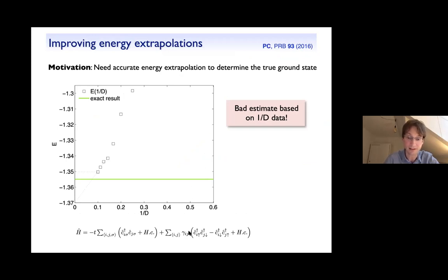That's for an exactly solvable model of non-interacting spinful fermions. The details don't matter, but the exact energy is shown in green here, this green line. And this is the iPEPS data plotted as a function of 1 over the bond dimension. You see the last point is a variational value, so it's above the true ground state energy. And then often if you take a linear extrapolation of the 1 over D data, you get something which is lower than the true ground state energy, because in the end we expect a faster convergence than in 1 over D. You see this is correct, the exact energy lies in this interval here, but the error bar is very large. So it's not very satisfactory.